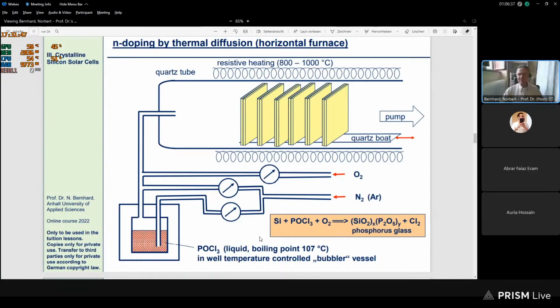You see, it's basically a glass. A glass is mainly silicon dioxide combined with phosphorus oxide, and chlorine is released here in this process. And then in the next step, when this phosphorus glass is grown, since we have quite high temperature, a substantial amount of the phosphorus will diffuse from this phosphorus glass into the silicon wafer, making the n-doped top layer and the p-n junction.